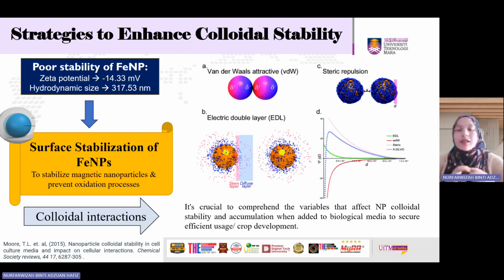So, nanoparticles are frequently stabilized by forming a dispersion layer around the external surface. The stabilization of suspension with high nanoparticle concentration depends on the creation of an electric layer at the proper thickness, while a narrow layer causes particles to aggregate. Thick layers produce an enormous restricted volume around the particle.